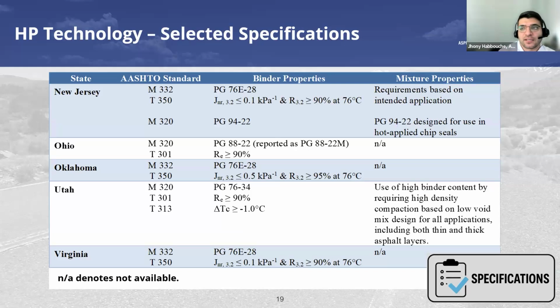So they perform their MSCR testing. They have a requirement on their Jnr being a maximum of 0.1 with a percent recovery of a minimum of 90% at 76 degrees C. The way Virginia handles HP mixtures, they have their typical mix. They just do a binder swap. They take their conventional PMA binder out, they put their HP binder in, they pave, nothing else is changed.